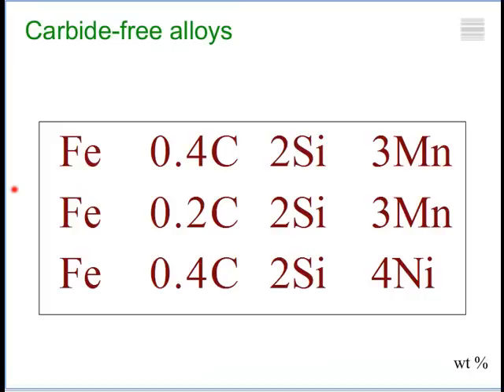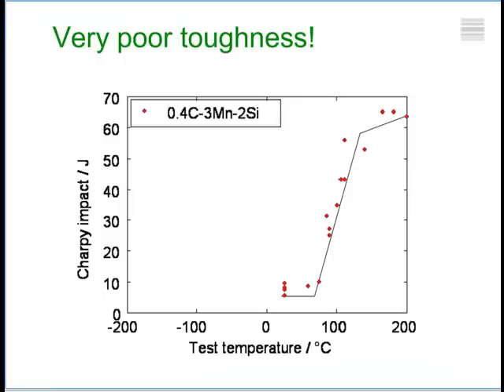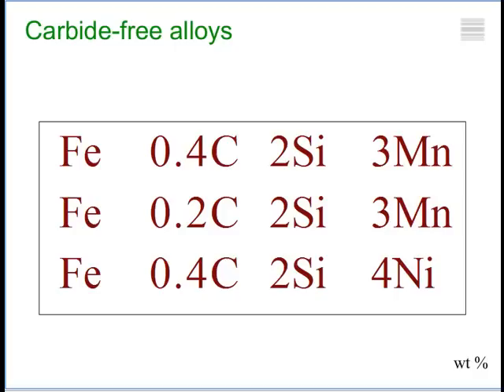Okay. Now, why am I bothered about increasing the fraction of bainite? Well, if I take the first steel here, 0.4 carbon, 3 manganese, 2 silicon, the toughness is terrible. This is 100 degrees centigrade for the impact transition temperature. There is nobody in their right mind who would use this steel for a critical application such as a pipe going down an oil well. You really want this curve to go down to much lower temperatures so that you can get good Charpy values at low temperatures.